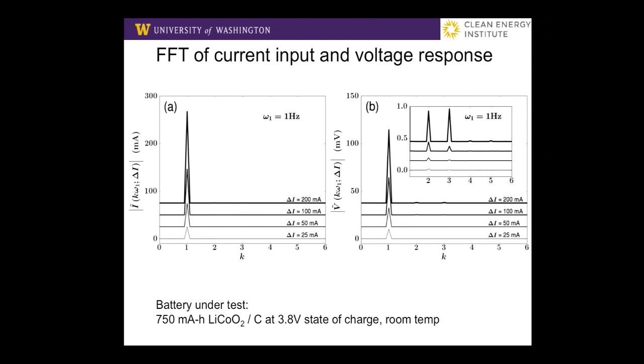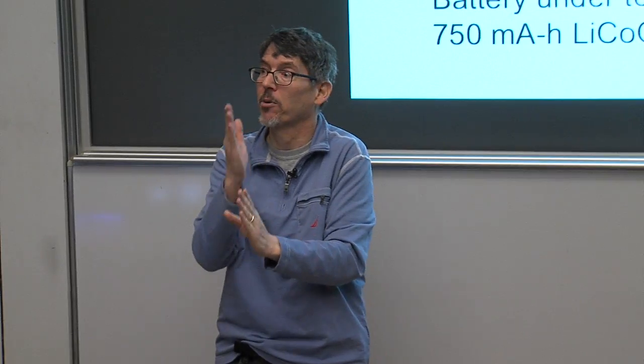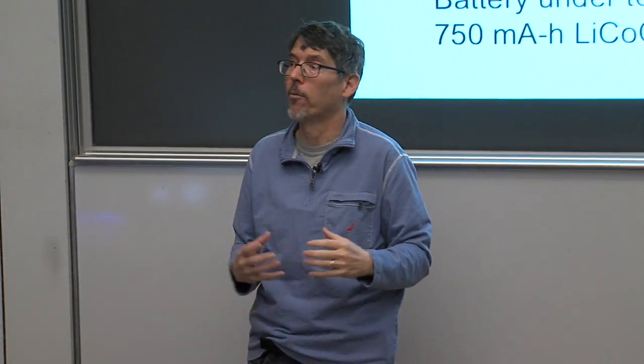Just these spectra tell us something. It tells us that this system is stable to the finite perturbations we're using. So one of the things that you always have to ask is, if I perturb something with a finite amplitude perturbation, does it jump to new states? For flow, that would be turbulence. For this system, it could be a full spectrum of different features, and the fact that we see discrete harmonics says this is a well-behaved system.